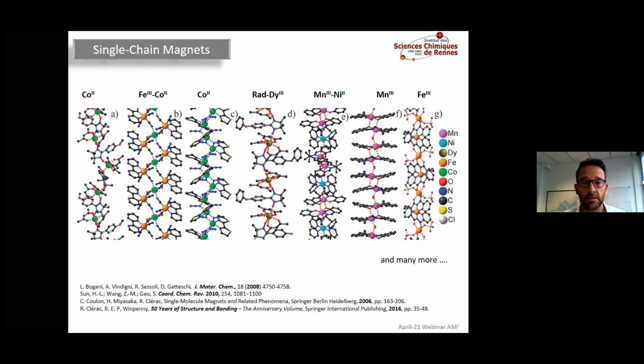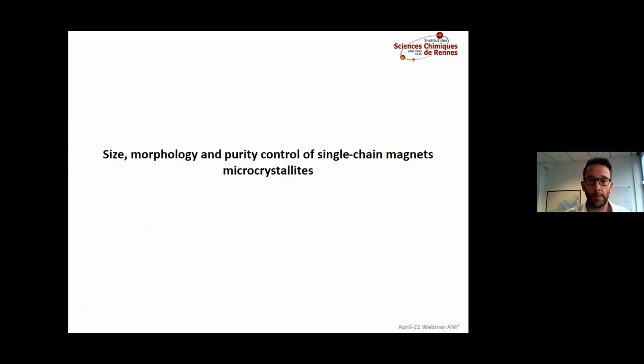You can synthesize them with a very large library of organic ligands, paramagnetic ligands. You can do it with 3d, 4f ions, whatever. So you just need anisotropic centers, and to be sure to shield magnetically the chains, to be sure that your magnetic behavior is confined inside the chain. So what we are trying to do now is to control the size, the morphology, and the purity of our single chain magnet microcrystallites.